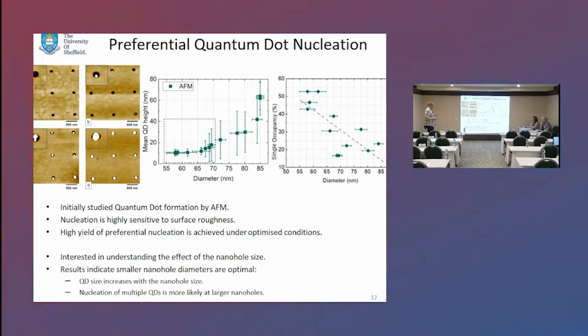And then also looking at, now this is single occupancy as a percentage, so anything that's empty or contains double dots doesn't count. And what we'd like is obviously for this to be as high as possible. So what it tells us is that at the 50 to 65 nanometer hole size, we can get a good number of sites containing only one dot.